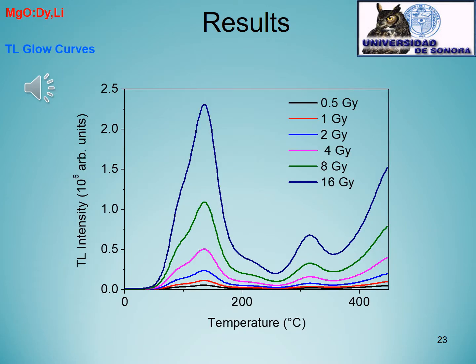Another remarkable result for magnesium oxide based materials is the one we obtained with dysprosium and lithium doping. We can observe from the TL glow curves that there is a very useful interval for medium doses, between 0.5 grays up to 16 grays.